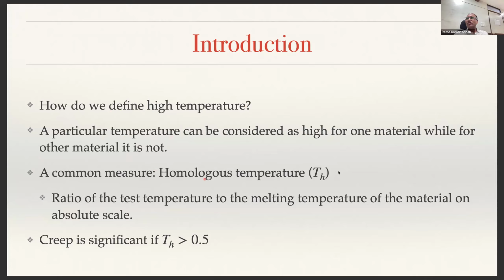So a common measure is what we call a homologous temperature, TH. What is homologous temperature? Homologous temperature is the ratio of the test temperature to melting temperature. That means if you are operating it at T and the melting temperature is Tm, T by Tm is your homologous temperature. Creep in a material is significant to be worried about if your homologous temperature is greater than 0.5. That means if your operating temperature is at about 50% of the melting point of that particular material, that is when you need to be worried about creep deformation. Otherwise, you need not worry.